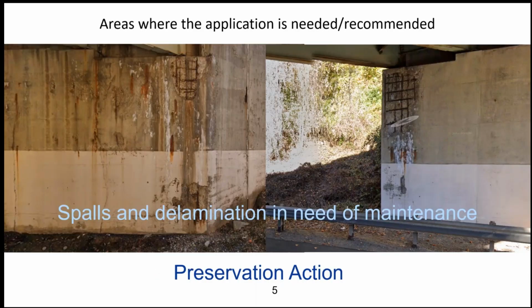So again, this is a close-up of the repair, and you could see the spalls where the corrosion of the reinforcement is visible. As preparation for the spray application, we removed all the loose and delaminated material, and of course sandblasted or pressure washed depending on the case. In this case, it was a sandblast to remove all the loose material and all the corroded steel residues. And this is obviously a preservation action to preserve the bridge for the long term. Next slide, please.